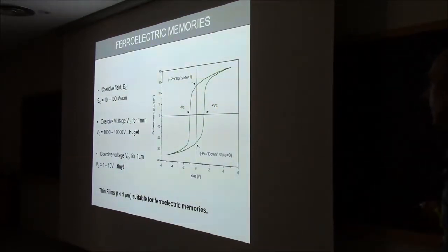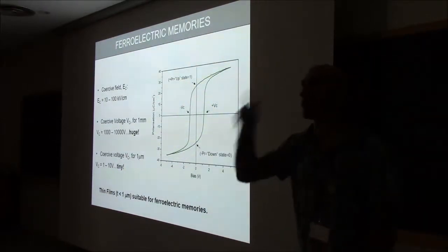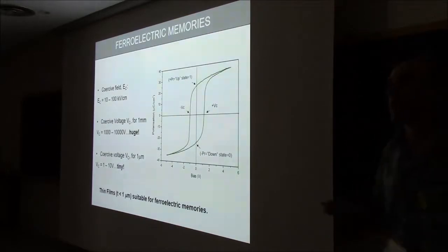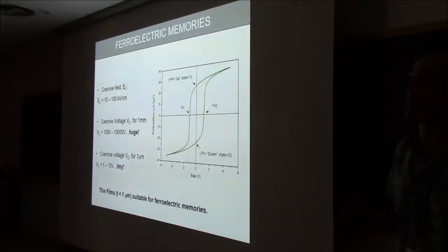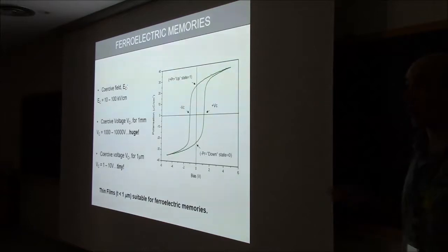Now, the coercive field that you need in order to switch the polarization from up to down, or from down to up, is usually quite big. It's thousands of volts per centimeter. So if you have a bulk single crystal and you want to switch it, you're going to need to crank your voltage up to thousands of volts. Not very useful, because you cannot have a 1000-volt battery in your mobile phone.